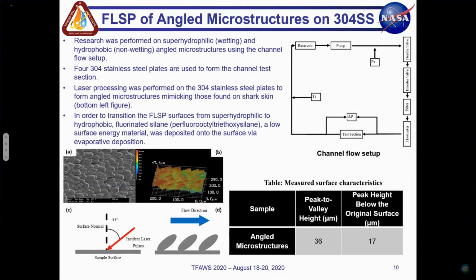The laser processing was done on the 304 stainless steel plates to form angled microstructures, which you can see in the bottom left image, which mimic those that we found on shark skin. By angling the laser itself, that's how we get these 35-degree angled microstructures that go in the direction of the flow. The peak to valley height of the structures, as far as the liquid is concerned, was 36 micrometers, and they are 17 microns below the original surface. So you are taking some material away.